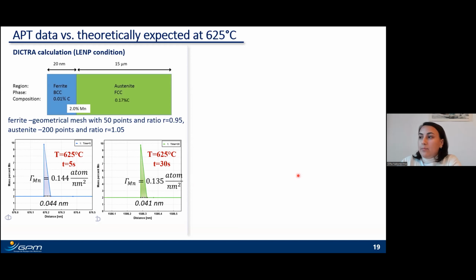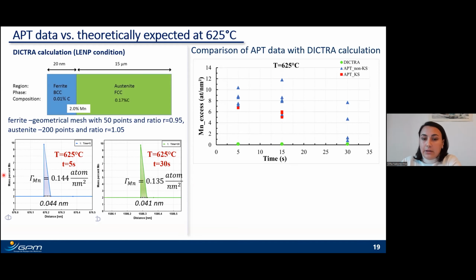And if we compare it with the experimental data, first of all, we see that the calculated manganese excess, here this green point, is not evolving with time, at least at the early beginning of the transformation, which is not the case in the experimental measurement. But what is more important is that it is several orders of magnitude different. The manganese excess value is really an order of magnitude different compared with the experimentally measured one. So, sorry.